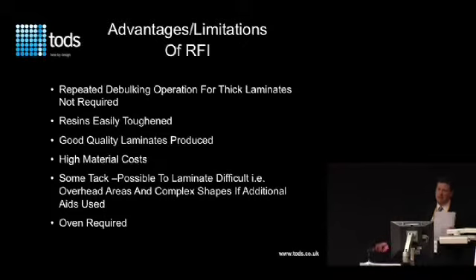The resins, again, are easily toughened. We find very good results with certainly the void content and reproducible resin content. Material costs, again, are relatively high, but the major disadvantage is you have tack, but it's not a lot of tack. So you can hold it in place, but you do need additional aids to be able to do that. And also you need an oven.